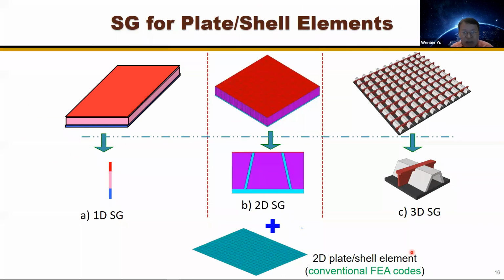Okay, how about when we have a structure like a panel with a lot of heterogeneous details, and we want to analyze it using plate and shell elements, say for example a bending problem and a buckling problem? Then it depends on how this structure is made. If it's made of homogeneous layers, then the SG will be the transverse normal line, because that is my smallest mathematical building block. I can use this line, sweeping in plane, to build that three-dimensional structure. If we have heterogeneity along one of the in-plane directions, I'm dealing with a two-dimensional domain. If I have heterogeneity along both in-plane directions, I deal with a three-dimensional domain.